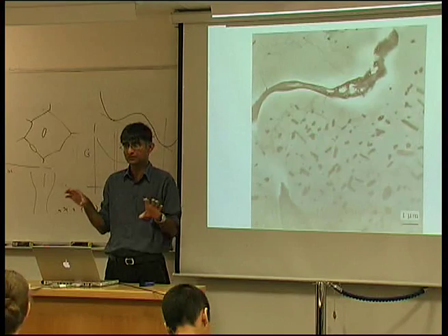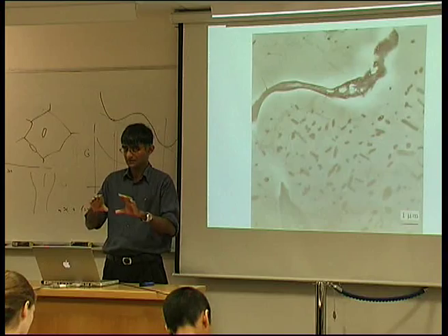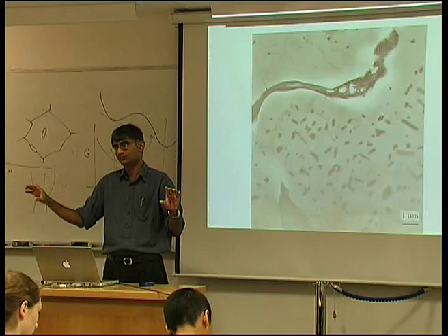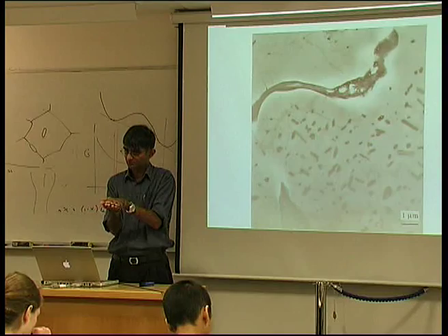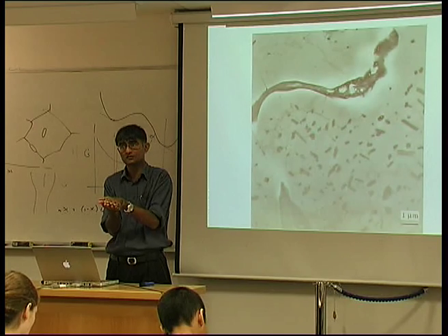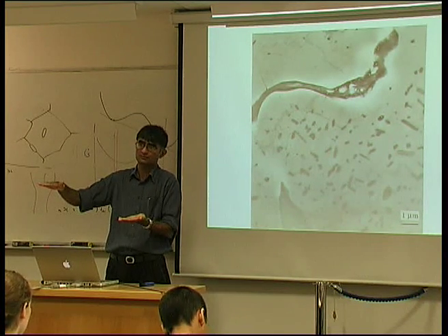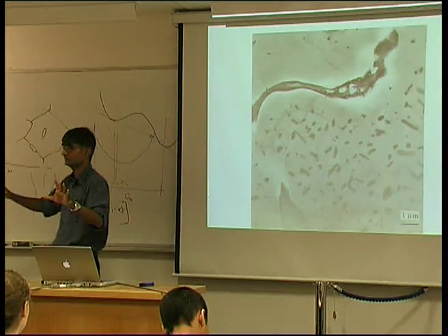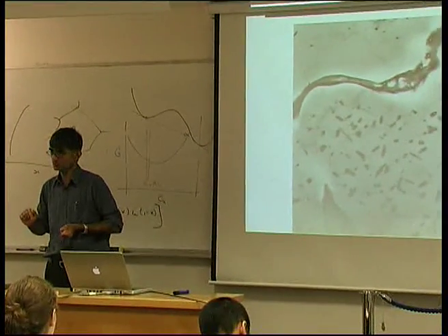That's why when we make aircraft, we have to have strong aluminium alloys which are precipitation strengthened. The alloys are clad with pure aluminium. Okay, so what you see on the outside is a thin layer of pure aluminium by roll bonding, and inside is the precipitation strengthened aluminium. So you make it much more corrosion resistant by cladding it with pure aluminium. So when you actually look at an aircraft, you're not looking at the aluminium copper alloys, but there's a thin layer of pure aluminium which prevents this corrosion problem.